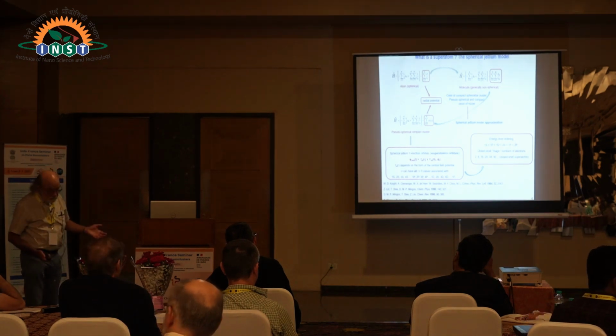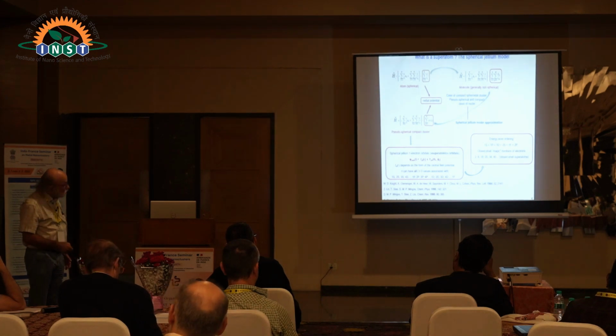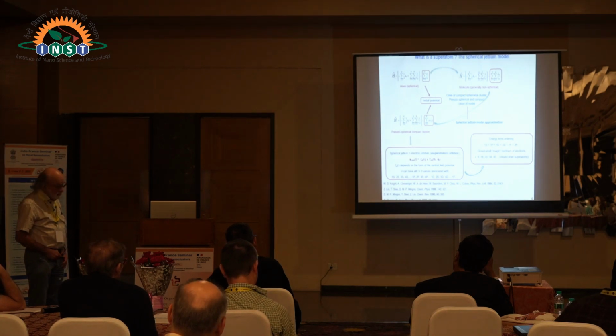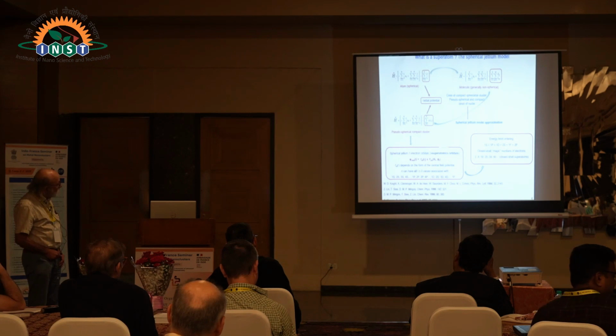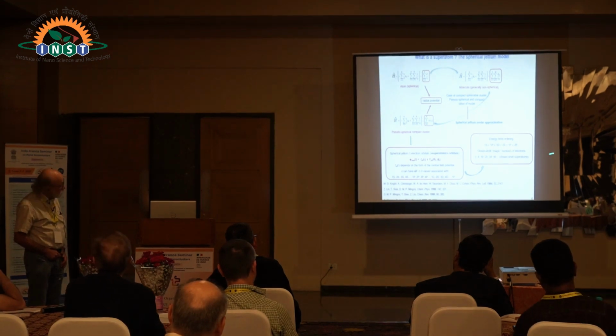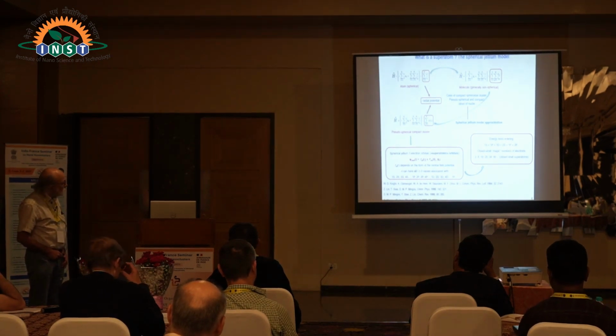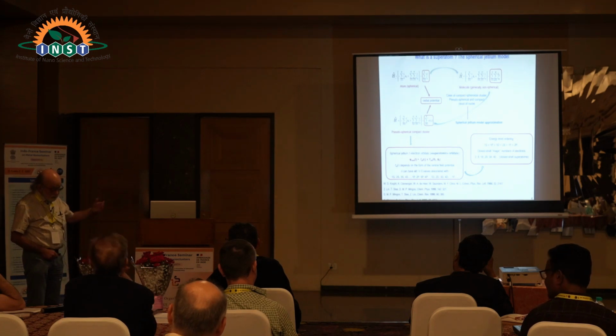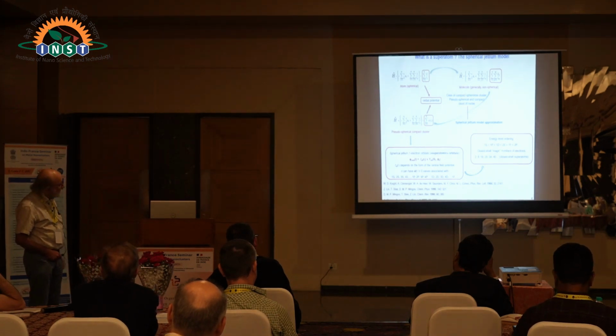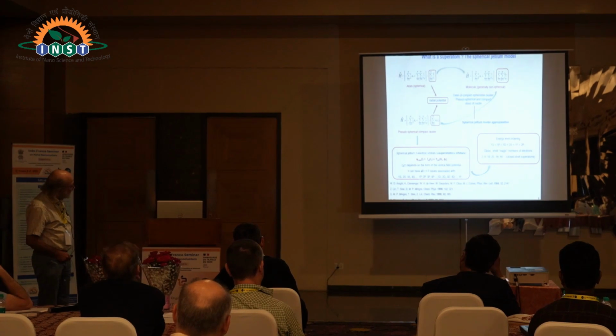And for the same reason as for a polyelectronic atom, it will be chemically stable when any of these shells, 1s or 1p or 1d or 2s and so on, is filled. So we will also have closed shell electron counts, which correspond to favored numbers of electrons in terms of stability. People call them magic. They are not magic, but this is their name.